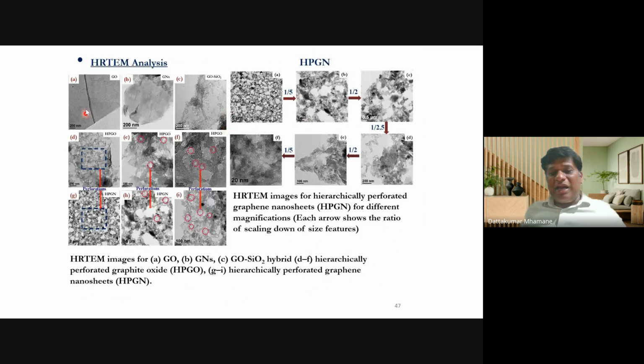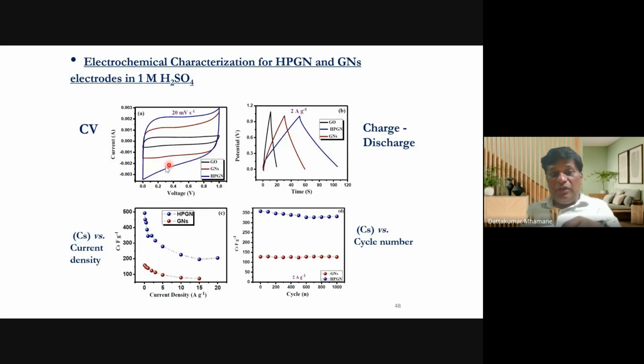So you can see here different size images of perforated graphene. This is reducing scale, one-fifth, one-half, then one-2.5. So you can see scaling down, and you can see the hierarchical pores present in the graphene structure. So what is happening if the pores are there? You can see here, this blue line is for perforated graphene. See the performance. We reach about 500 farad per gram in the case of perforated graphene. But this brown one is without perforation, it has not even reached 200 farad per gram. But in the case of perforated graphene, we reach about 500 farad per gram specific capacitance.